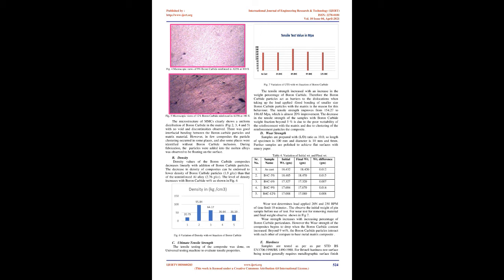The microstructure of MMCs clearly shows a uniform distribution of boron carbide in the matrix, Fig. 2, 3, 4, and 5, with no voids and discontinuities observed. There was good interfacial bonding between the boron carbide particles and matrix material. However, in a few composites the particle clustering occurred in some places, and some places were identified without boron carbide inclusion. During fabrication, the particles added into the molten alloy were observed to be floating on the surface.